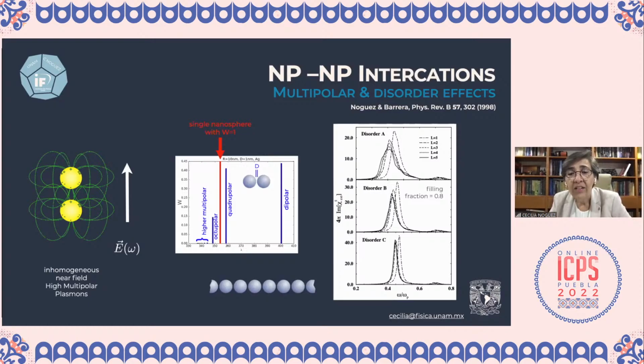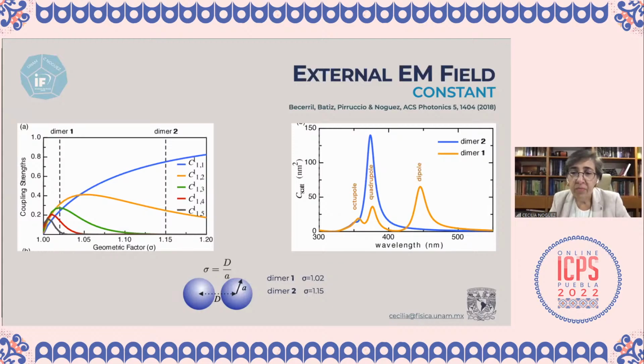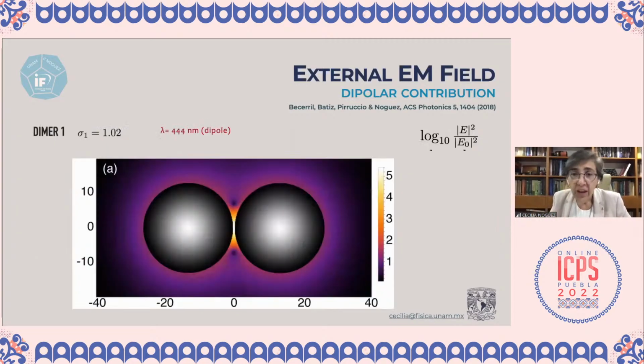And well, we can look at how much the distance and the array of the nanoparticles are contributing to this response just by looking at different kinds of disorder, let's say, along a chain made of these nanoparticles. So we can have this kind of modes now. Instead of having a single response, we can have different peaks just because we are changing the distance between two spherical nanoparticles. Okay, and also we are modifying the external electromagnetic field, the near field contribution.